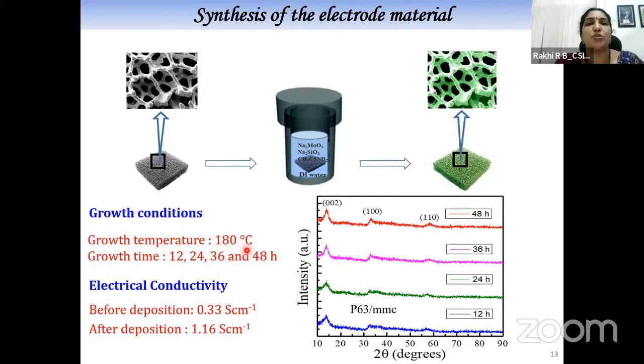And hydrothermal growth was performed at a temperature of 180 degree Celsius, and we have done it for different growth times. That is also from our previous experience with other samples, we know that the growth temperature and growth time play a major role in determining the morphology as well as the electrochemical performance of any material. Then we did it in two different ways.